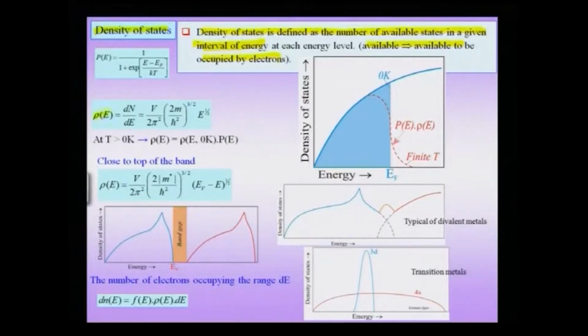So, I can calculate my density of states as dn by dE, with the n formula as I showed you before, and therefore, if I do this differentiation, I would find that the density of states goes as E power half. In other words, if I plot my density of states with energy in the free electron model, it goes like an E power half kind of relationship, and at 0 Kelvin, you know that only the energy levels up to the Fermi level are filled, which we pointed out. In other words, all the energy levels below the Fermi level are occupied, which is given by the blue region in this plot, and all the energy levels above the EF level are vacant.